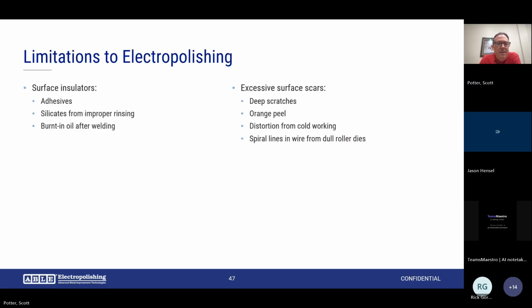Since electropolishing is more used on the micro side, deep scratches, things you can feel when you rub your thumbnail across, typically won't be removed when you're taking 5/10,000 to a thousandth of material total. Orange peel condition, you see that when people are forming either tubes or wire, where the grain boundaries become very pronounced. The orange peel is something that we can't overcome. Distortion from cold working, nicks, dings, large defects are typically not going to come out with electropolishing.